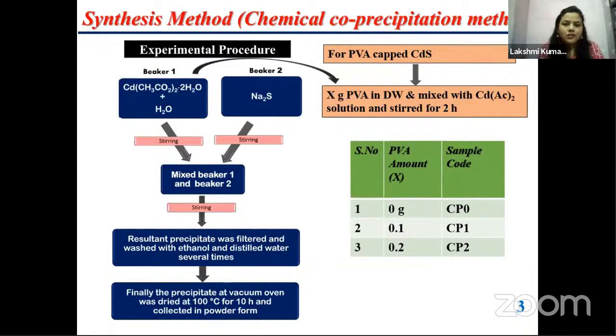So we have synthesized this material by using the chemical co-precipitation method. For the preparation of pure cadmium sulfide, I have chosen an appropriate amount, that is 0.5 molarity of cadmium acetate, and dissolved it in distilled water. After that, it is placed on a stirrer for stirring, and then an aqueous solution of sodium sulfide is added to this cadmium acetate solution, and both are stirred for some time. After that, the resultant precipitate was filtered and washed with ethanol and distilled water several times. Finally, the precipitate was vacuum oven dried at 100 degrees centigrade for 10 hours and collected in powder form as CdS nano powder.